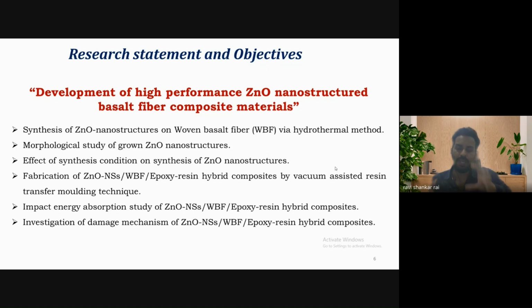So here we plan to do some secondary reinforcement, which has been done using the zinc oxide nanostructure. The research statement is the development of high performance ZnO nanostructured basalt fiber reinforced polymer composite, in which we have synthesized the ZnO nanostructure on woven basalt fiber via the hydrothermal method. Morphological studies and the effect of synthesis conditions have been done, and we have fabricated the sample with the help of vacuum assisted resin transfer molding. After that, we have analyzed its mechanical characterization using impact testing and the damage mechanism.